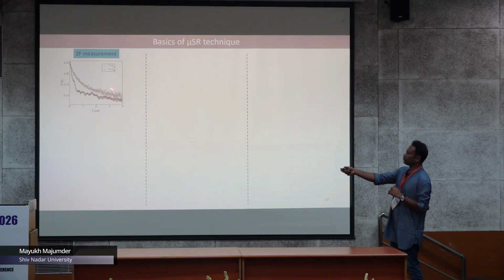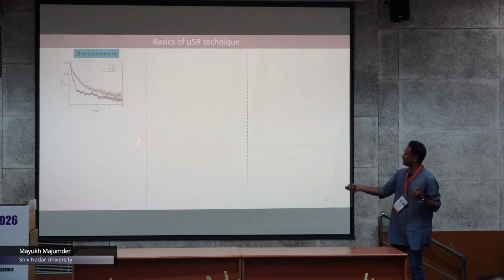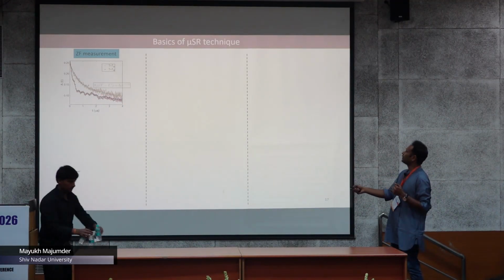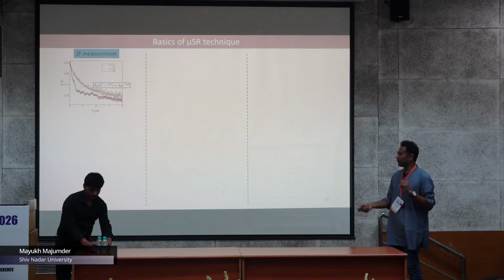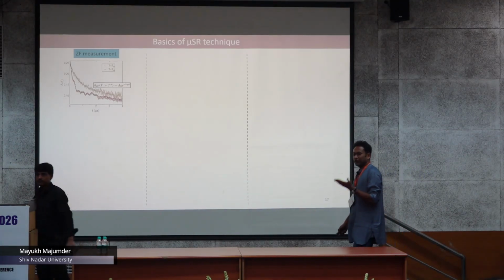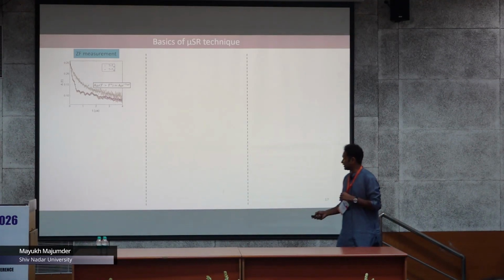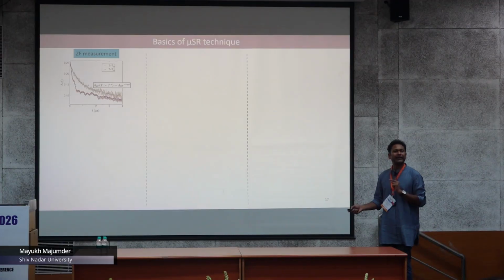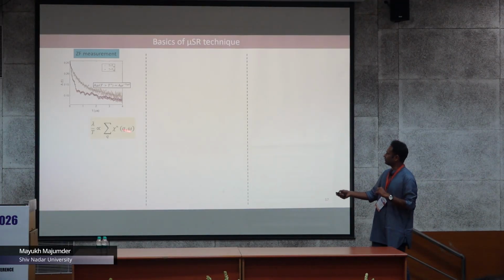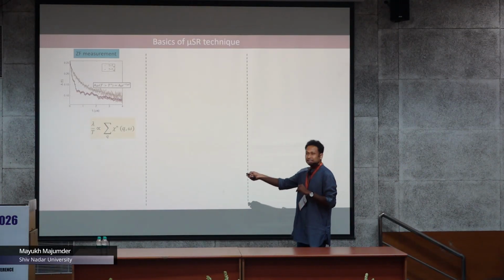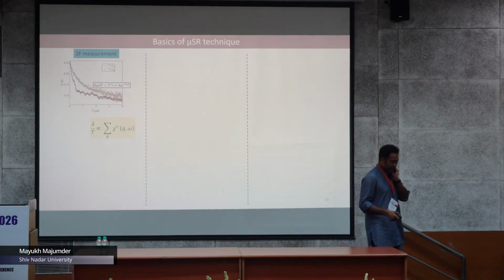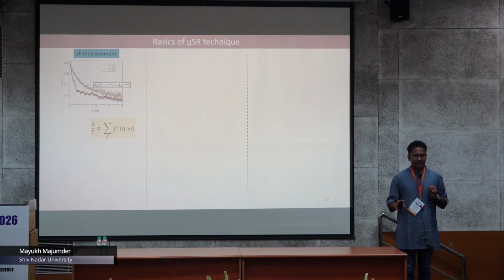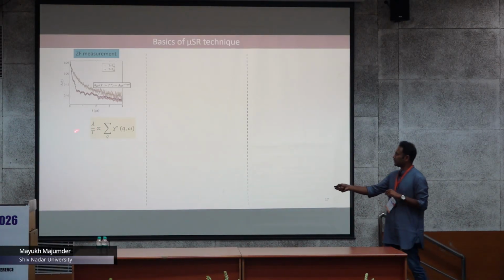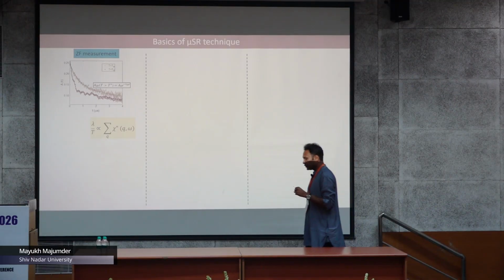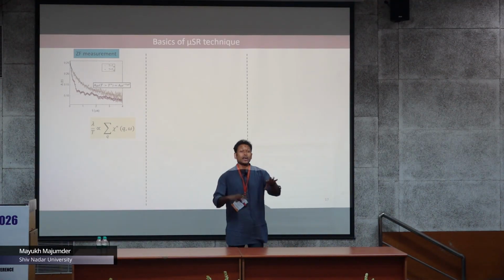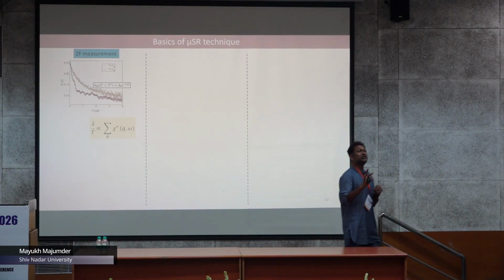But if you are thinking about what is happening in the paramagnetic state, there is of course no oscillation, but you can fit the data with some exponential function and extract the relaxation rate, the muon relaxation rate. Before going further, let me tell you that this lambda is actually proportional to the imaginary part of the dynamical spin susceptibility. So the temperature dependence of lambda is going to give you information about the low energy electron excitations or low energy spin dynamics.